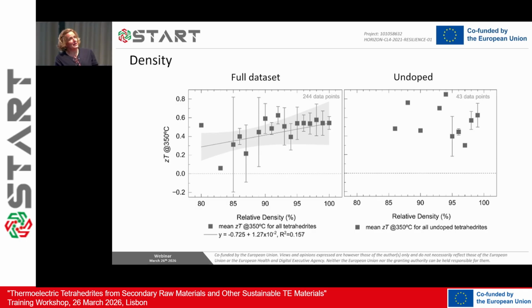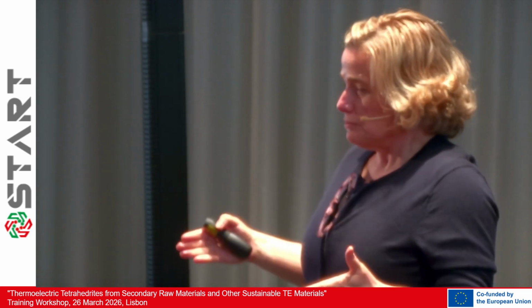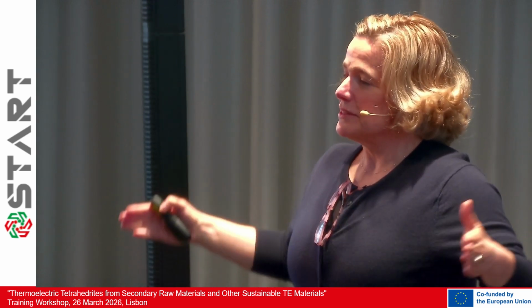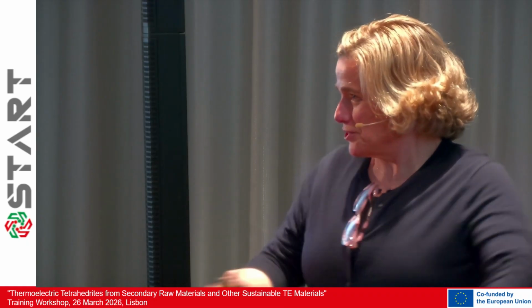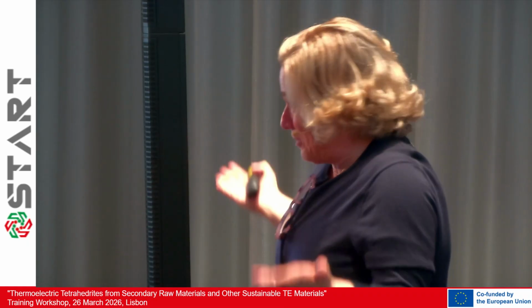Do we see any influence of relative density on ZT? Again, relative density is complicated because even for undoped material with a single composition, the theoretical density used by authors ranges quite a lot, which is very strange.